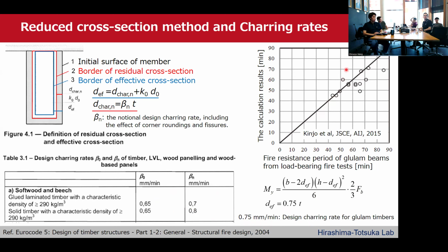This figure shows that the result obtained by the reduced cross-section method generally agreed with the fire resistance period obtained from the load-bearing fire tests of glulam beams. The reduced cross-section method can adequately evaluate the resistance of mass timber elements during ISO standard fire heating. On the other hand, when considering the behavior up to the cooling down phase after fire exposure, it's inappropriate to evaluate the resistance using the reduced cross-section method.